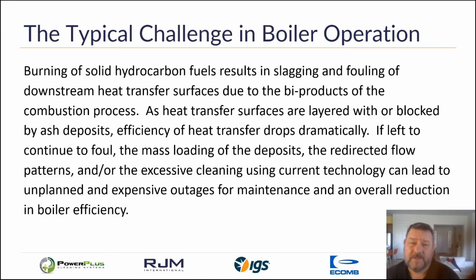If left unchecked, the mass fouling will cause redirected flow patterns and loss of efficiency. Excessive cleaning via the traditional soot blowing methods can cause thinning or pitting of the tube surfaces, eventually leading to tube leaks and expensive and unplanned outages.